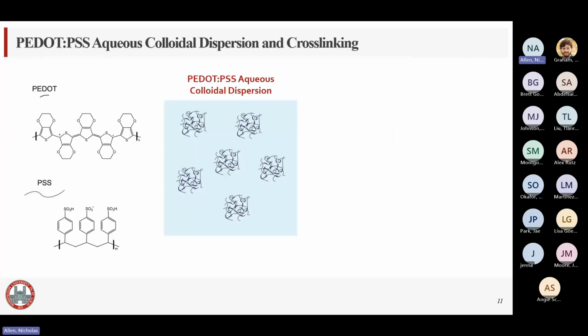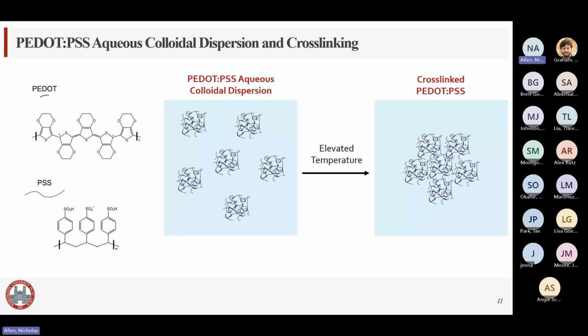And what does an aqueous colloidal dispersion look like? Essentially, you have nano and micro scale aggregates of positively charged PEDOT electrostatically attracted to negatively charged PSS distributed in a large amount of water. And what we know about this colloidal dispersion that I was particularly interested in and saw potential in was that elevating the temperature of this aqueous colloidal dispersion can bring those PEDOT:PSS aggregates together and cross-link them to form different PEDOT:PSS materials.